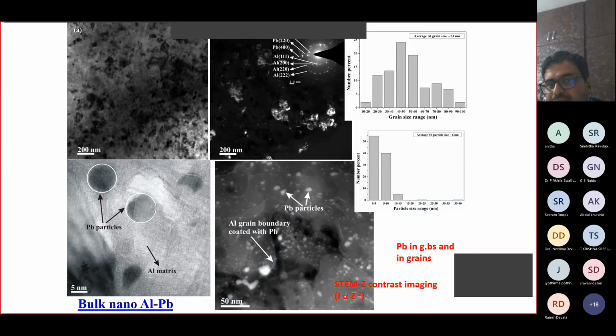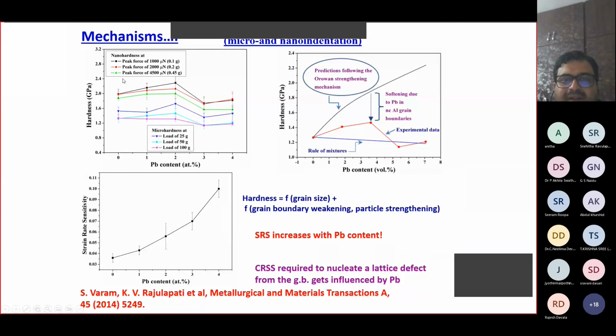This only tells us about the locations where aluminum and lead are sitting. So this is a large aluminum grain, large in the sense this is 50 nanometers. You can understand what I mean by large, and also you have a smaller lead particle sitting in it. So that makes a perfect scheme for dispersion strengthening. And we have explained all these things based on the modified Orowan analysis, and also by incorporating nanoscale mechanics into this. Okay, so I'm not going into the mechanics, the in-depth research part of it, because that's not important for the FDP. But if any of you are interested, please ask me these questions later in the interaction session.